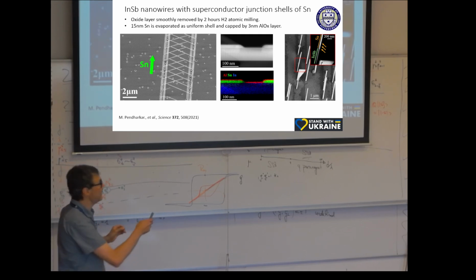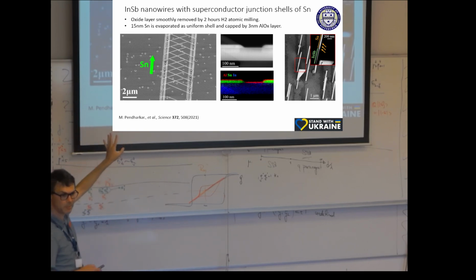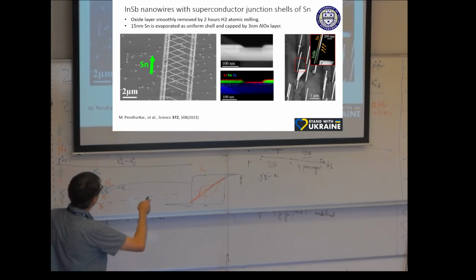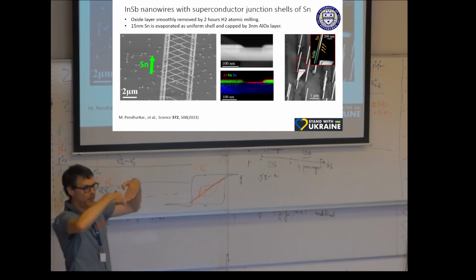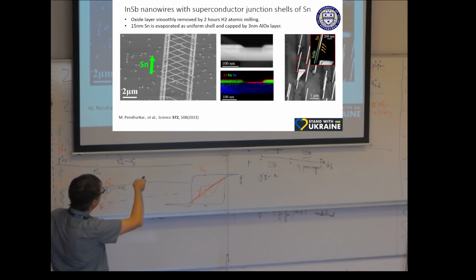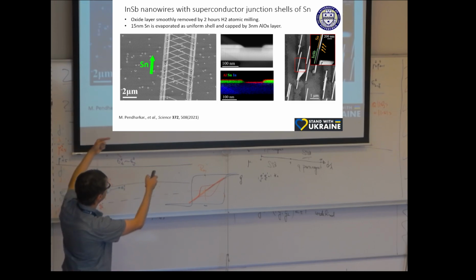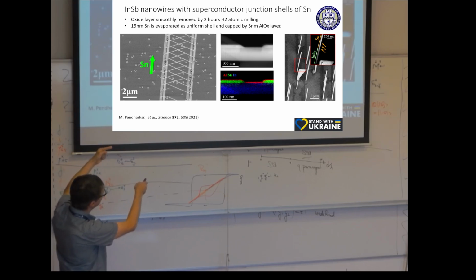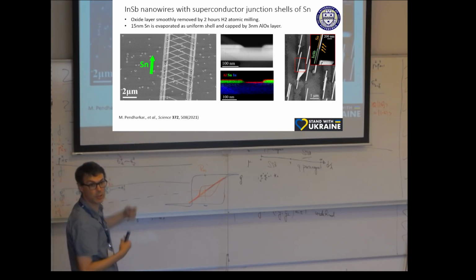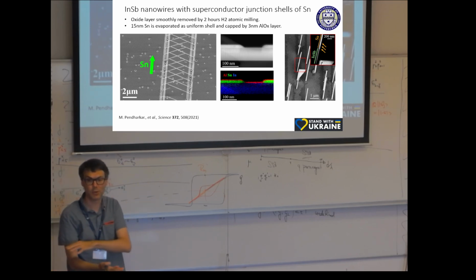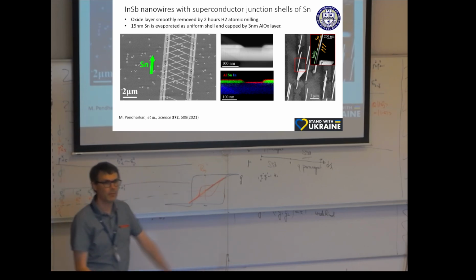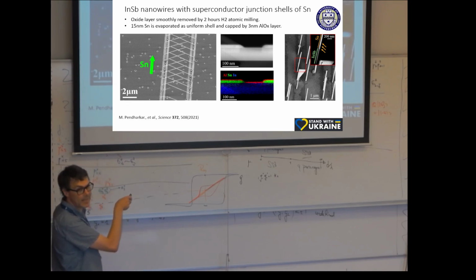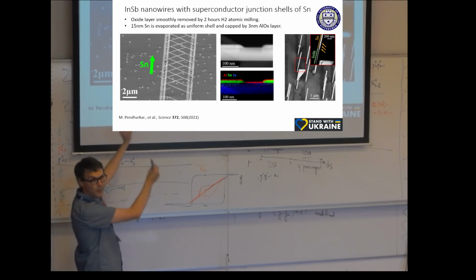These are really quite amazing junctions. They are not the ones we used for the first measurements, but they are the ones we use right now in the lab. These are indium antimonide nanowires, and they are grown. We etch trenches, which are notches like this, and we put gold catalyst particles from which wires nucleate at very precise locations along the trench, so that the wires grow. There's a relationship between the crystal, the wire and the substrate, and because it's at an angle, they grow in this crisscross. Imagine we went from laying down carpets of film, micron size long, to precisely positioning nanoscale particles of gold and nucleating these perfect crystals.